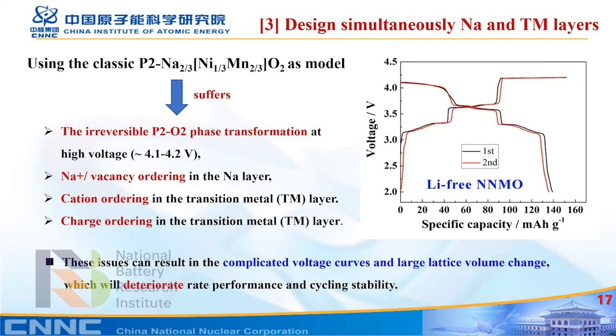Because NNO suffers from a lot of problems, such as the serious P2-O2 phase transformation at high voltage, the voltage from 4.1 to 4.2 volts, and different ordering processes, including sodium vacancy ordering in the sodium layer, the cation ordering and even charge ordering in the transition metal layer. It has been proven that these issues can significantly degrade the voltage curves, capacity, and cycling stability.